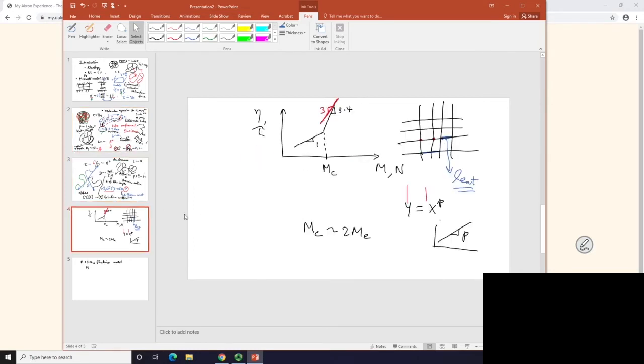When you think of this in the abstract way, with chains reaching out to each other, then again, when the chain is as short as less than twice the entanglement length, how can they form a network? They cannot reach each other anymore, right? You see the point, when they are too short.